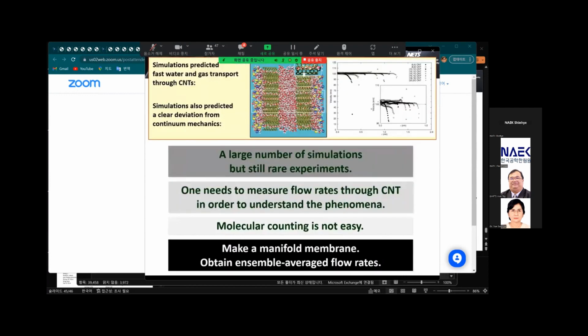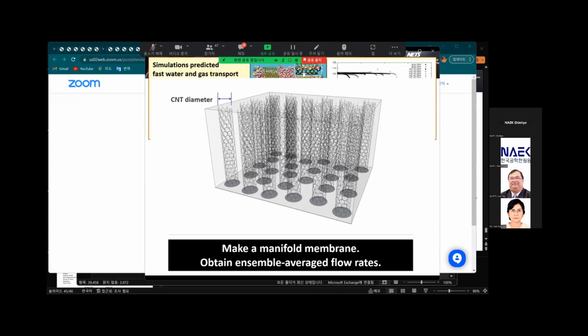Perhaps the best way to resolve this conundrum would be to establish experimental data for various carbon nanotube diameters. Unfortunately, counting water molecules is technically impossible at the moment. An idea to bypass this technological difficulty is to make a manifold membrane and obtain water transport rates in an ensemble-averaged way. To this end, narrowing down the carbon nanotube diameter distribution within the membrane is significant. If we have 1-nanometer-wide channels here and 5 nanometers there, the data would be close to garbage.